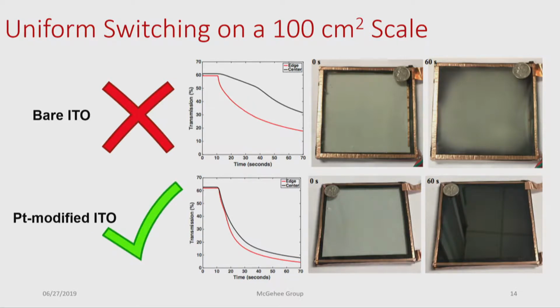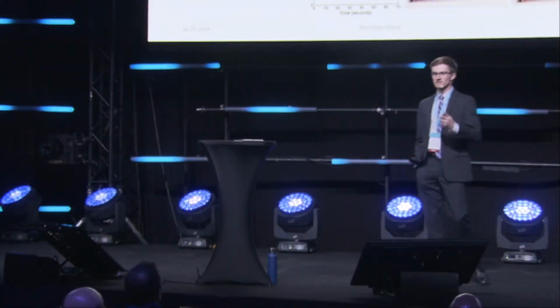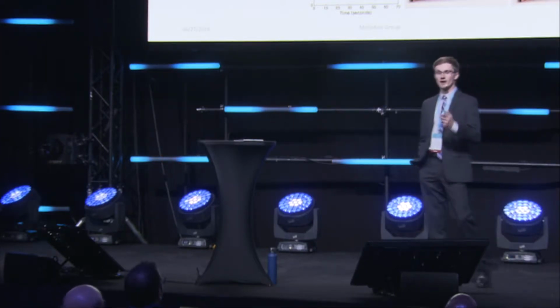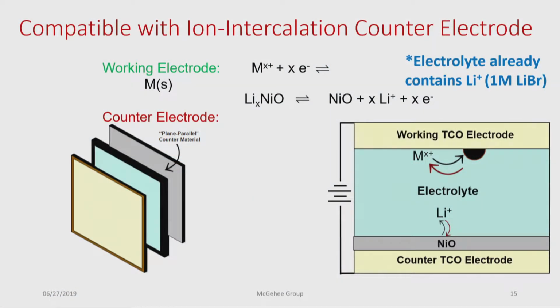Okay, so now that we've tackled both the working electrode and the electrolyte, it only kind of makes sense to tackle the entire electrochemical cell. So we wanted to look at potential counter-electrode materials. One great thing about this metal system is that it's compatible with ion intercalation materials, commonly found in batteries or other electrochromic technologies. So this material on the counter electrode will usually intercalate ions such as lithium, which is great because there's already a high concentration of lithium in our electrolyte, which was initially there for ionic conductivity purposes.